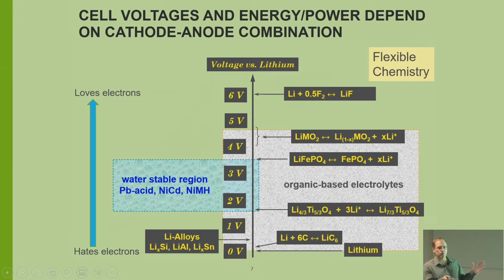So now we have a 4.4 volt battery, whereas before, with your alkaline batteries and your lead acid, you're limited to like 1.5, 2 volts. So we got almost a 3 times increase in energy and power just by getting rid of water and going to a carbonate-based solvent. Carbonates can go up to about 4.5, 5 volts, and they can go down close to the lithium potentials. As I said before, nothing really survives lithium potentials. There's one material that's slightly lower, but for all purposes, lithium is the bottom of the power table.